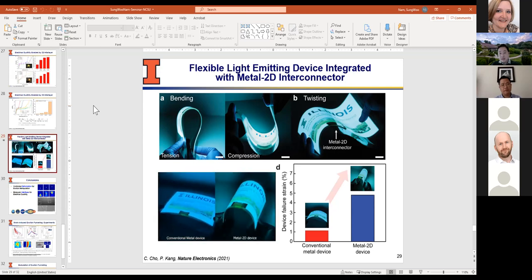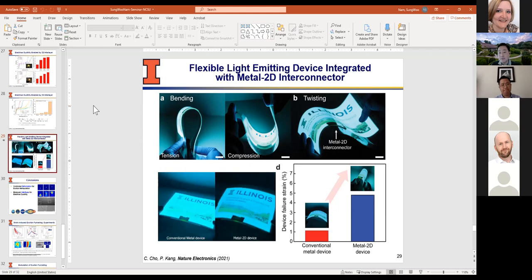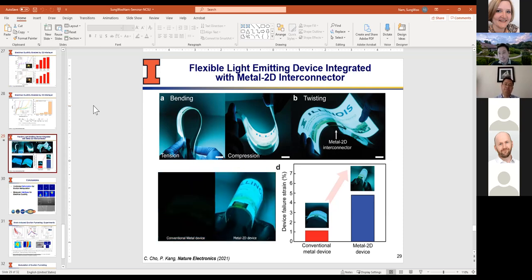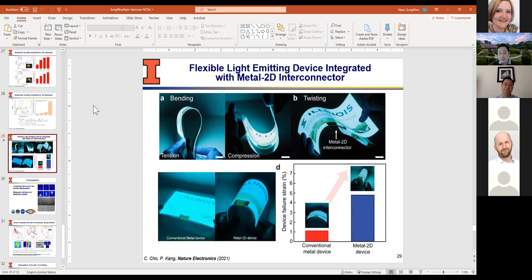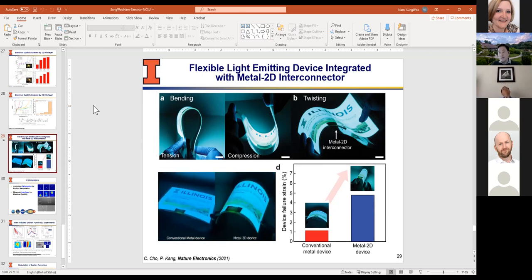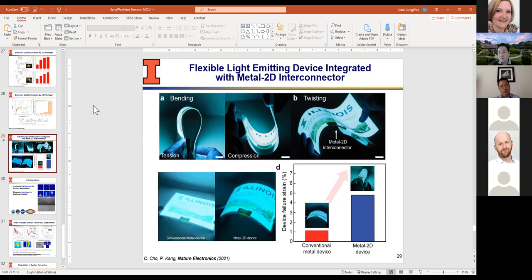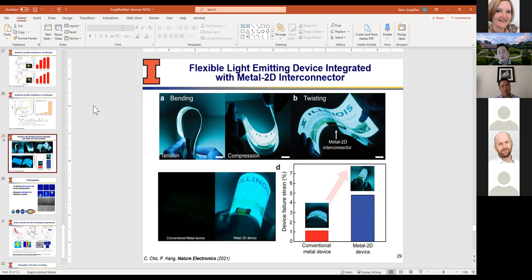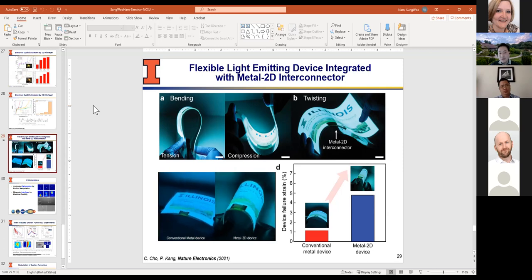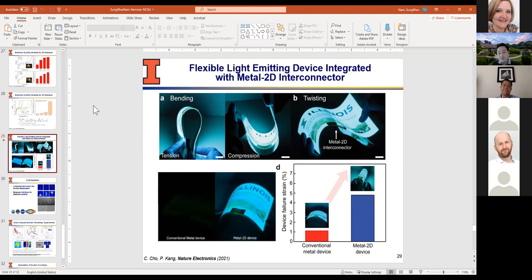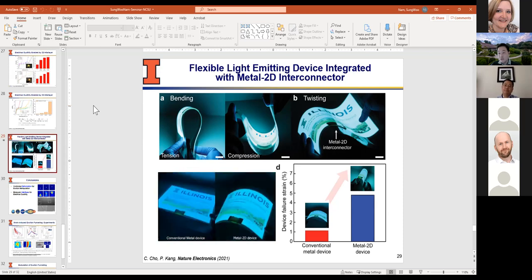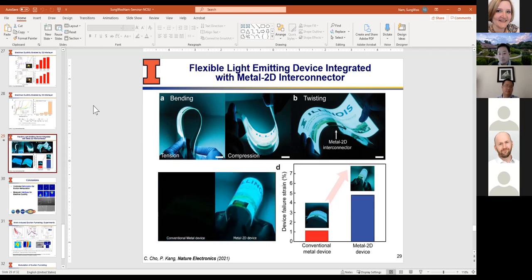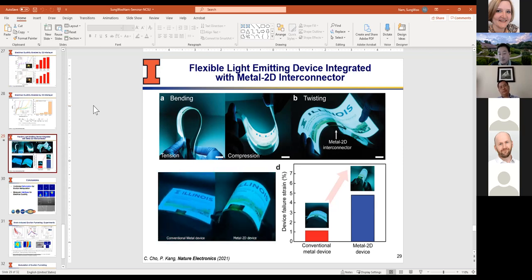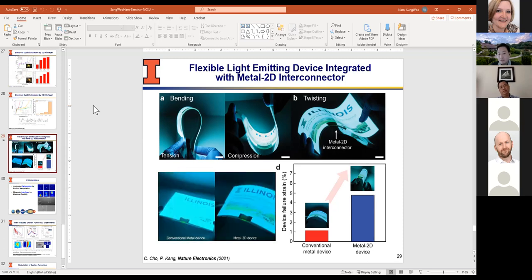I think people demonstrated that if it was a photo sensor, photodiode, or emitting diode, you could use strain to change the color. But again, it's only 50 millielectron volts, so you don't see that color change. It's very, very small. Spectroscopically, you see that. But if you are worried about drift, then it needs something more like a heterogeneous strain profile on the surface or on a substrate. So for lots of potential applications it may not go as far, but there are definitely changes to the optical band gap energy of these materials with respect to strain. People probably need to consider that if they deal with any optical properties of these materials. Yeah, that's pretty interesting. Thank you.